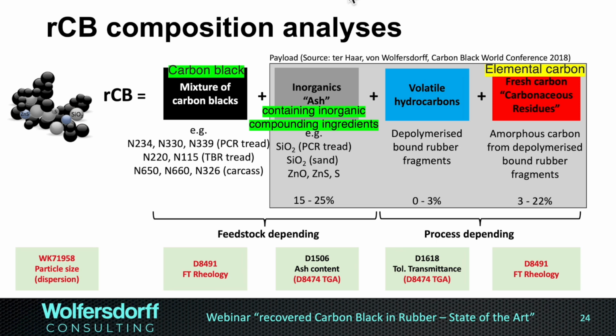We test in the green rubber, so in the unvulcanized rubber, and we're looking at the frequency response of the third wave, and we compare that to the base wave. And that gives a quick test. We only need 40 grams of recovered carbon black. We need to do compounding, so we might need a micro compounder to do a rubber recipe, but then we can go on this test, and I really like it for a quick test.